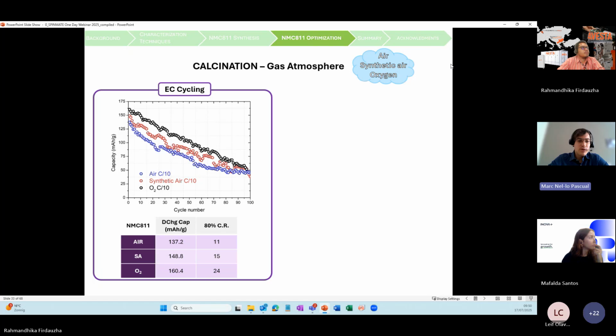lithium. So when we did the electrochemical assessment of these materials, we saw that both of these materials showed better electrochemistry. The synthetic air showed a discharge capacity of 150 with 15 cycles of capacity retention. And the oxygen material even got a better performance with 160 milliampere hours per gram with 24 cycles.